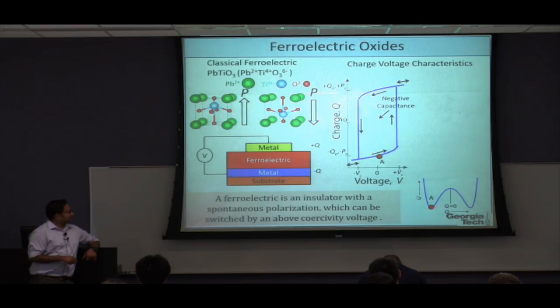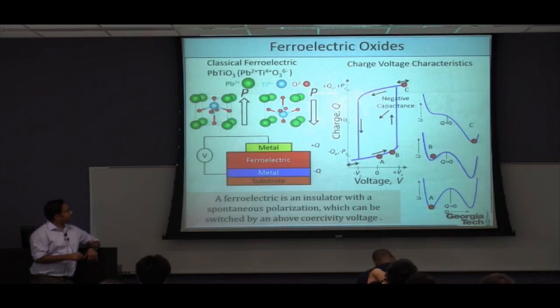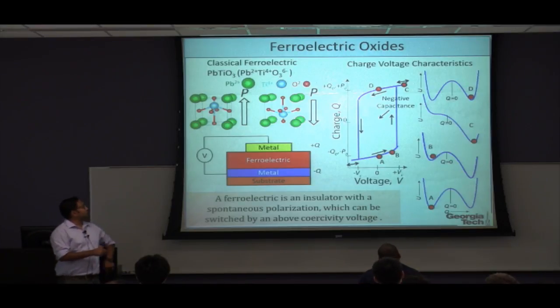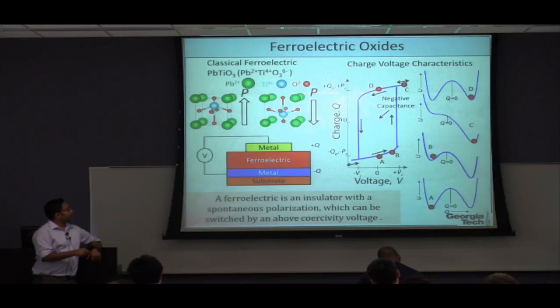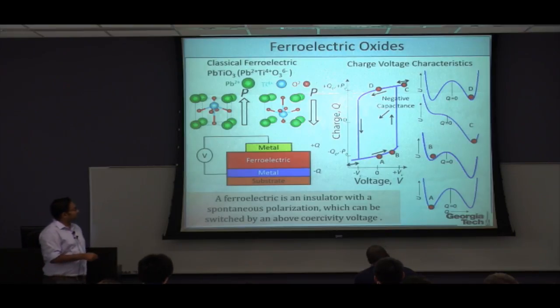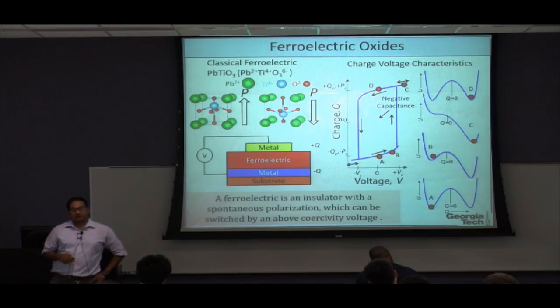Now, say we are here at this minima, which is quantified by A, and we apply a voltage. What will happen is that the energy landscape gets tilted and the polarization changes along this charge-voltage characteristic. Once we apply a voltage larger than the coercive voltage, it switches to the other direction here. And then once we bring the voltage back to zero, it goes to the other minima, the other direction of polarization. So essentially, by applying voltages, you can create a situation where the polarization starting from this position can move to the other position here.